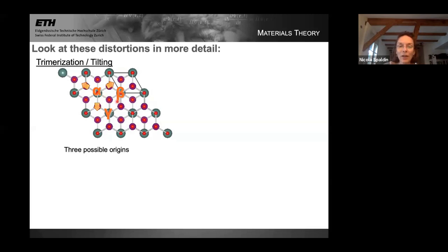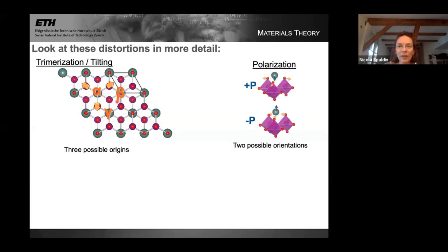There's another degree of freedom though. Around each of these origins, the tilting can happen in the out direction or the in direction. If the polyhedra all tilt out, then the yttrium on top drops down to fill the space and gives me a polarization in one direction. If the polyhedra tilt in, then the yttrium in the middle gets pushed up out of the way and gives the opposite polarization. So for each of these possible tilt origins, there's two possible orientations, and this should give me six domains.